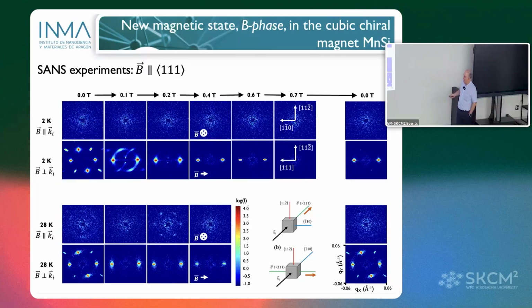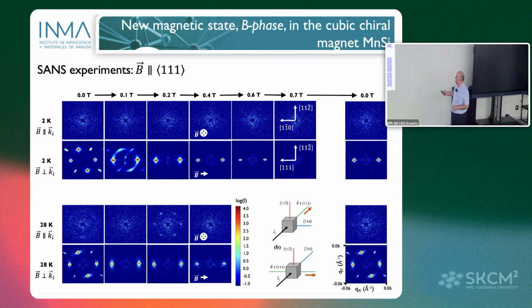If you do the same in the skyrmion lattice area, 28 Kelvin, with 2 configurations, we can see that in this parallel configuration, we can find the skyrmions here, only with a certain magnetic field, and then nothing. And the 4 diagonal domains are also developing, and at the end, you have only 1 diagonal domain. And at the end, at this 28 Kelvin temperature, you recover multiple domains. You don't have only 1 single domain. You recover the same. Remember the phase diagram. I will put it later.